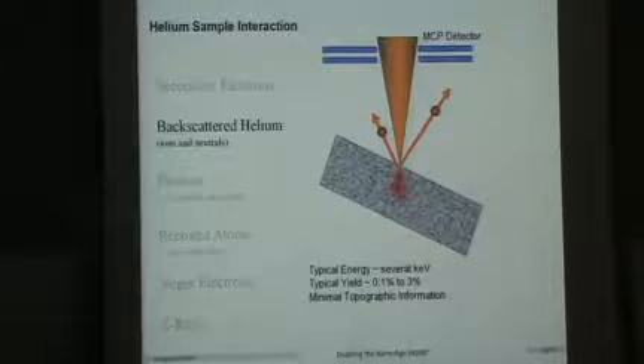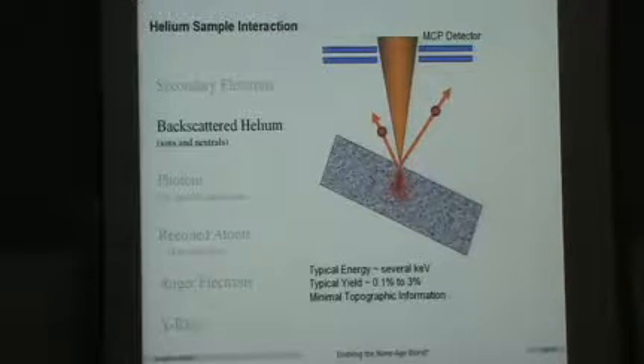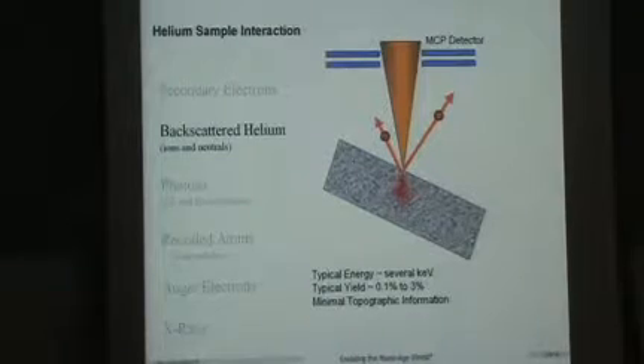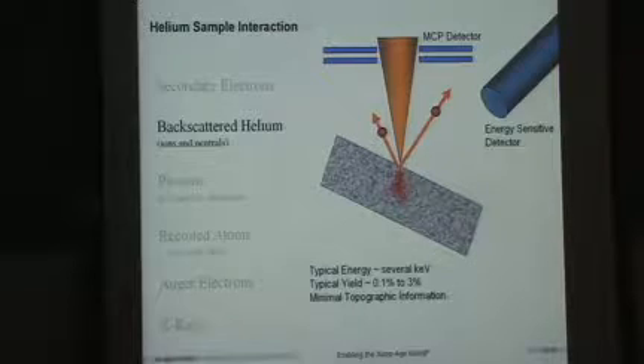There's also backscattered helium. The helium that went in, some fraction of them, typically a percent, sometimes a little less, sometimes a little more, some fraction of the helium that goes in will bounce out. That tells you some really interesting stuff. If you take a look at the scattering probability, the cross-section, it goes as the atomic number. So this gives you very good Z contrast. I'll show you an image of that a little bit later. But also you can take a look at the energy of those backscattered heliums. If you put in an energy-sensitive detector, you can actually deduce the mass of what you just scattered from. It's the classic two-body scattering problem. If you know the scattering energy and the scattering angle, you can deduce the mass of what you just hit.